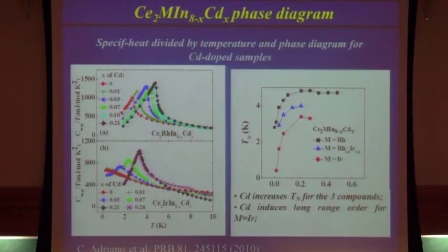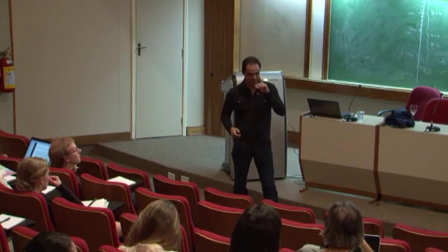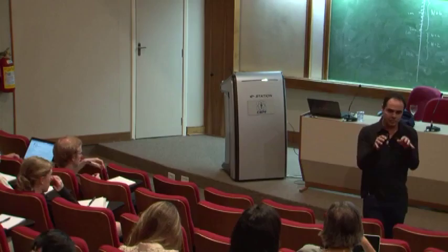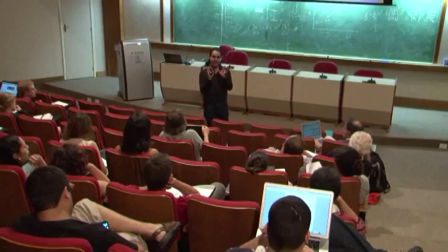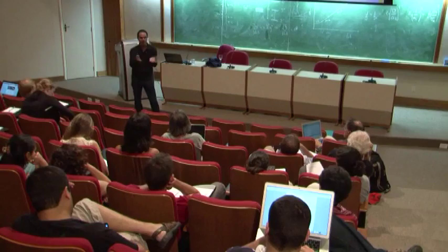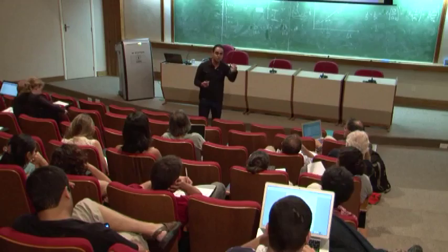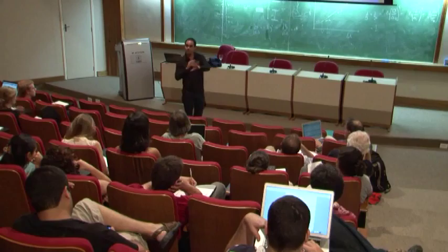Does cadmium act as a physical pressure at all? Is it bigger or smaller? Yes, it does. That's right. Both tin and cadmium introduce a little bit of distortion, but it's not the main effect. That's very small, and the main effect is the charge transfer at the indium site. NMR has seen that. When you put a cadmium there, you locally create a bubble of antiferromagnetism. So the electronic tuning is more important than the chemical pressure for tin and cadmium. Lanthanum is just chemical pressure.